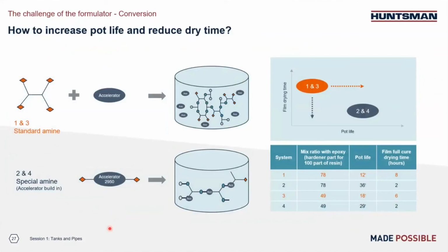So another factor we need to consider in terms of formulation design for improved degree of cure is using accelerators. People use accelerators to keep up the speed. A lot of times we add accelerators with amine and epoxy resin, and we have this kind of quick dry system. But because the accelerator does not have functionality to cross-link to the backbone, a lot of times those accelerators will leach out and compromise the system performance. So we designed a very special accelerator, which is 2950. We build the accelerator function into the amine backbone, right? And because of the low functionality of this special amine, we can speed up the cure but also maintain good pot life.